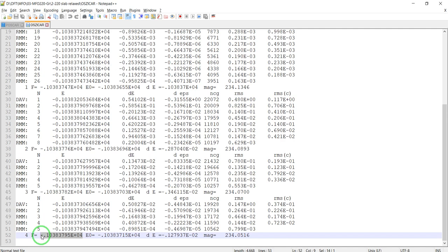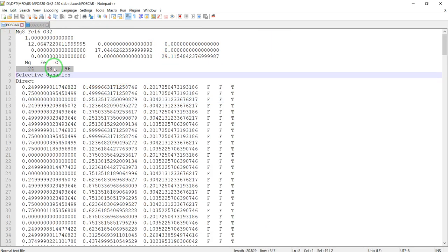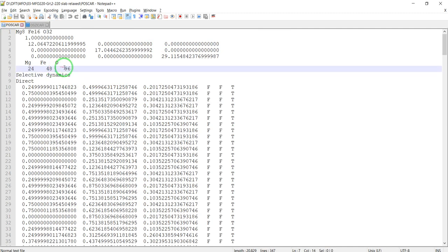There are two important points in calculating surface energy in this step. First, you need to be cautious about the number of atoms. If your slab has the same amount of atoms as the unit cell, then it's okay, but sometimes we add more layers to the slab. For example, here it's twice the size of the unit cell. You need to divide this energy by two here.